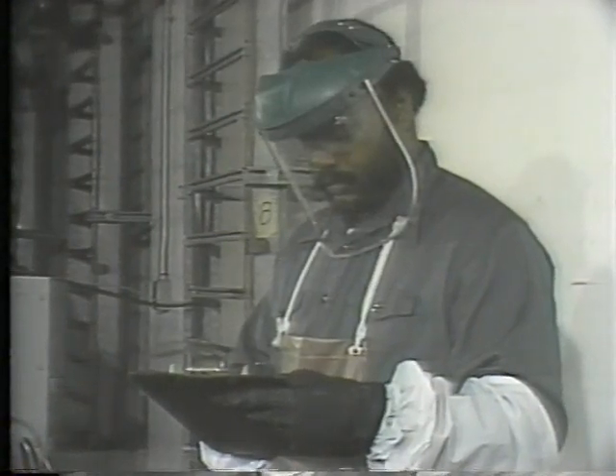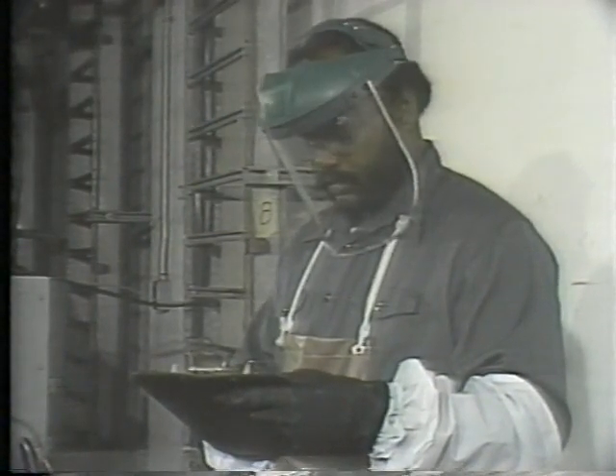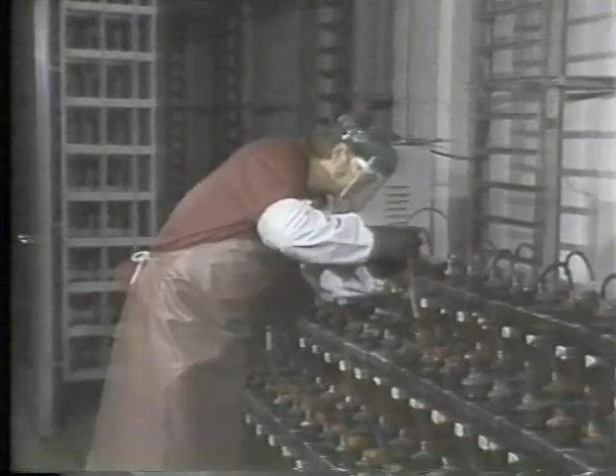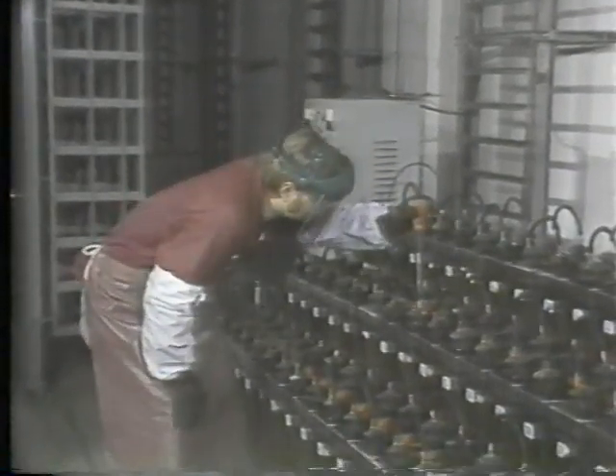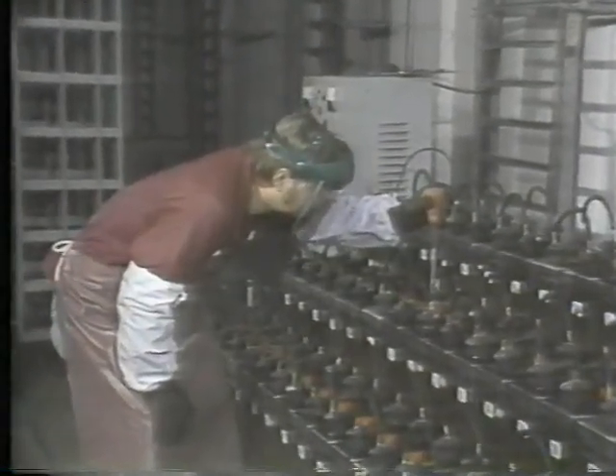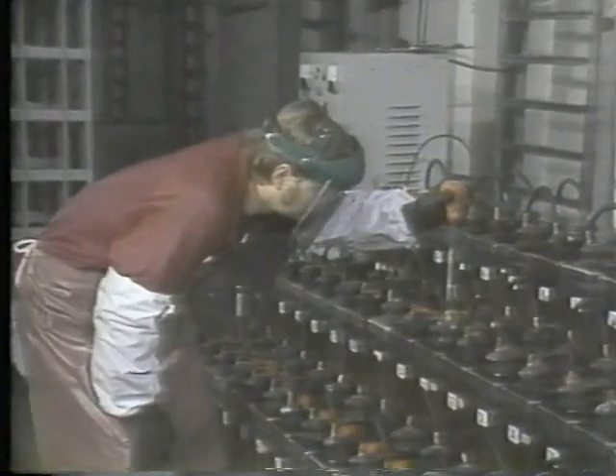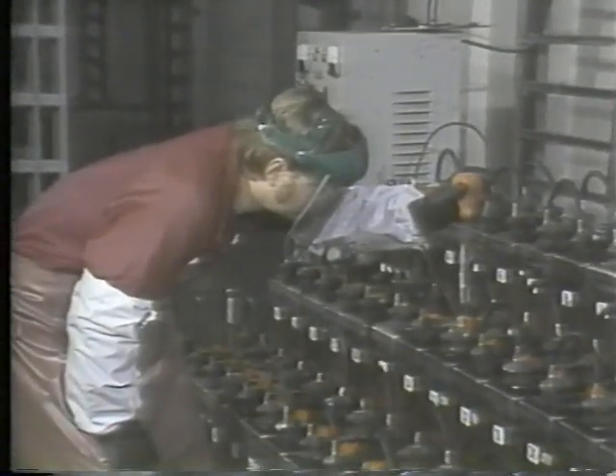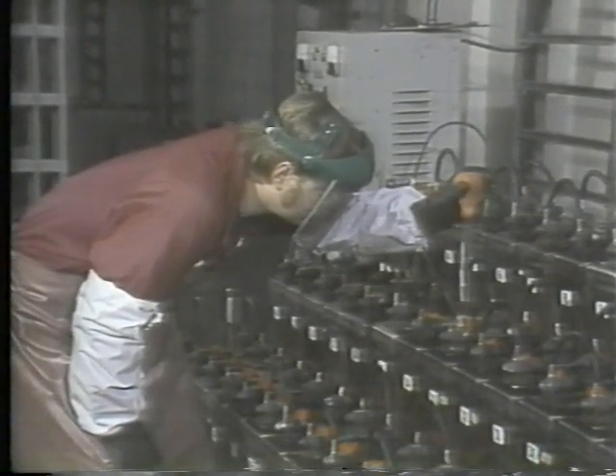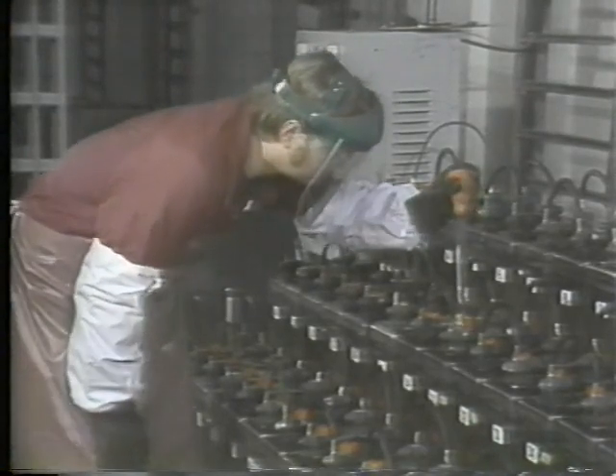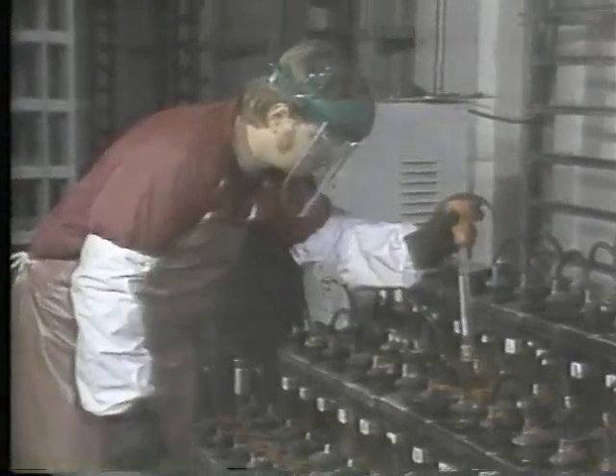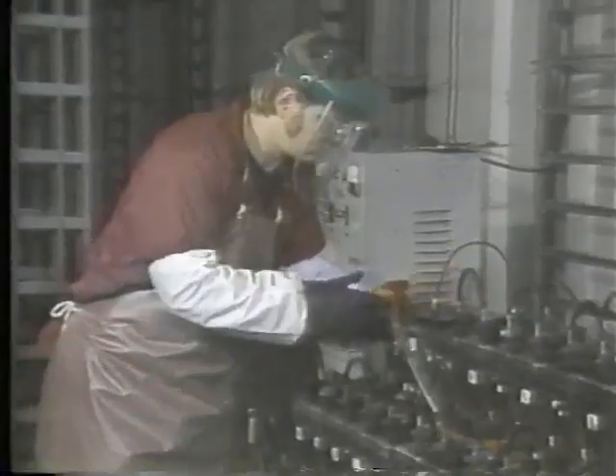Second, hydrometer readings have to be corrected for temperature. Most hydrometers are calibrated to give correct results at 77 degrees Fahrenheit, which is 25 Celsius. Lower or higher temperatures will make the electrolyte either more or less dense, even though the acid concentration is unchanged. In this case, after all the readings are recorded, the corrections will be made according to the temperature of the pilot cell.